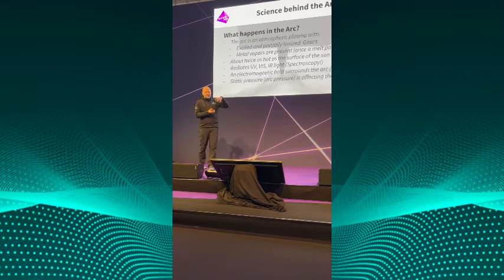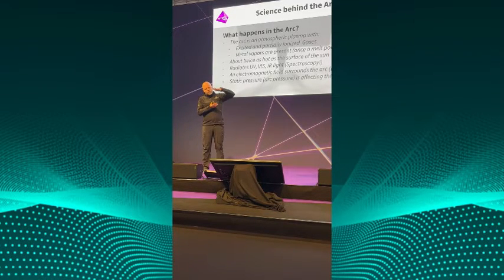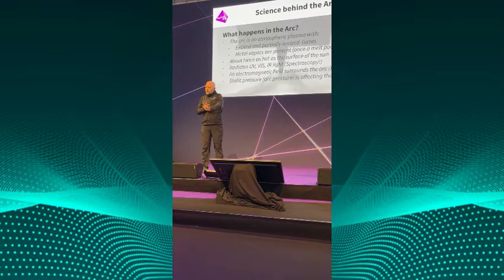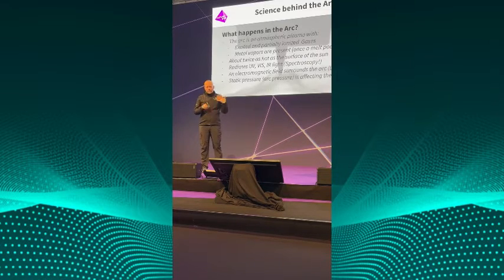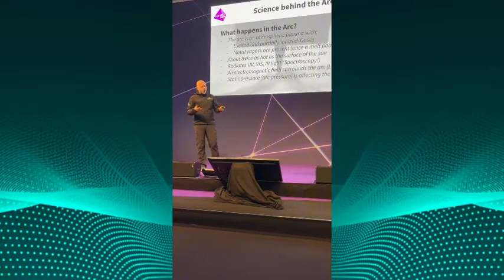Noticeable, there is a physical effect, a static pressure from the arc affecting the weld puddle. With very high current, you can indent molten metal just by the arc force. It's called arc pressure.